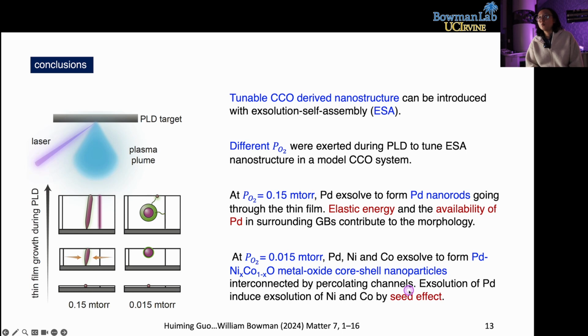In this work, we use exsolution self-assembly to introduce different and controllable nanostructures in the complex concentrated oxides, CCOs. And we tune the exsolution extent, like oxygen partial pressure, to change the nanostructures. At 0.15 millitorr, we found palladium nanorods growing through the thin films, and the elastic energy and availability of palladium in the surroundings will contribute to the formation of the nanorod morphology.